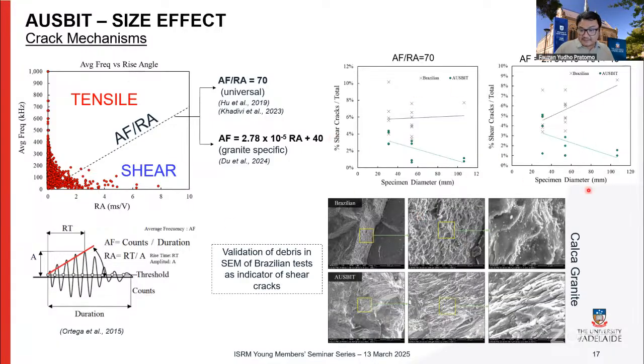The percentage of shear cracks tends to decrease with size in AUSBIT, and the opposite in the Brazilian test. This also interestingly validates the finding of debris in the SEM in our previous part, of the Brazilian test, as one indicator of shear cracks happening, because we know that in the Brazilian, we have a larger amount of shear cracks.